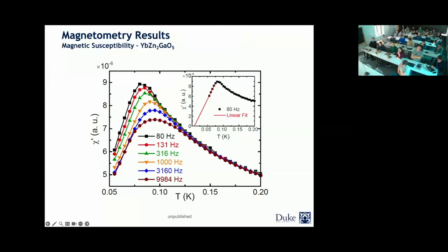So this is an indication that there is something going on, which we need to understand because it's giving us a peak, but that peak doesn't show a clear frequency dependence that would say that you have a spin freezing of the state. We anticipate that this is coming from orphan spins, because even when you try to have the perfect crystal in experiments, there may be some defects, and we think that they may be coming from those defects.